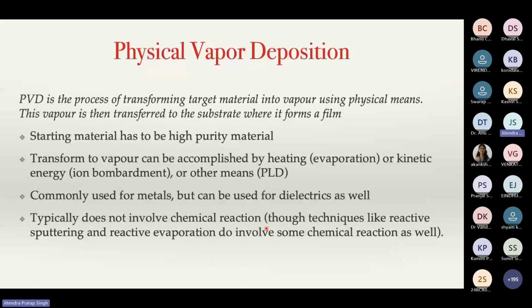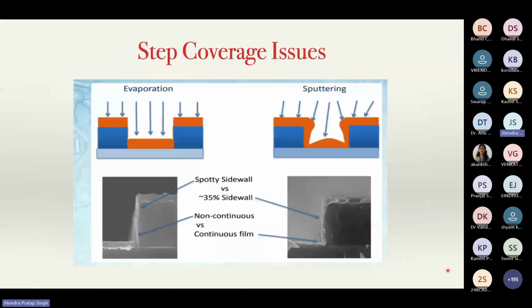Now, there are many methods here. I'm just giving you the idea of the advantage. If I use thermal deposition, where you thermally evaporate the material, or a normal e-beam deposition, then you get this coverage. Suppose this is some film which gets deposited on the pattern here. The problem will be the side wall. The side wall will be spotty, so it won't be deposited well if we use a normal thermal deposition. But if you go by the sputtering system, because ions are hitting from all the places and coming towards the substrate from all directions, they deposit very well. So in the case of sputtering, it's a very useful technique. You get a continuous film on the side wall also. That is one of the advantages here.